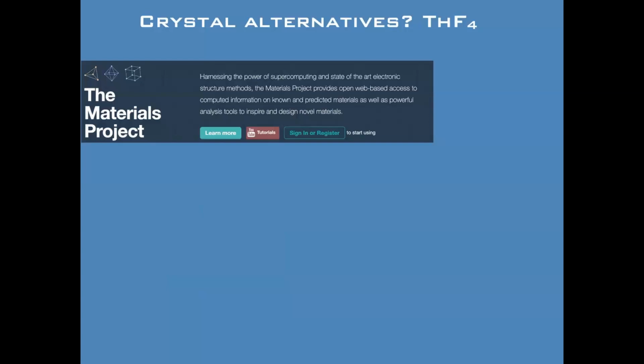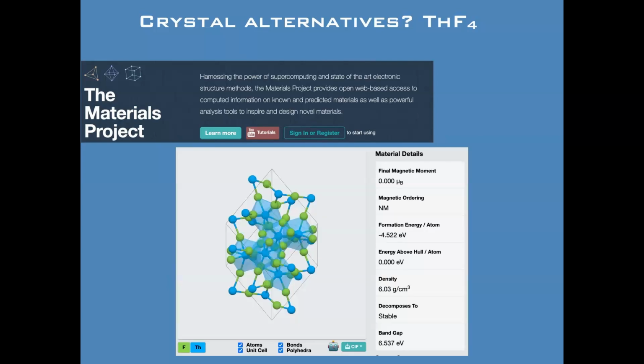But it would be nice if you didn't really have to dope into a crystal. If the thing you wanted to put in was native to that crystal anyway, then you don't get states within the band, and that's got to be helpful. So you immediately think of thorium fluoride. We had always wanted to use this, but if you go to the Materials Project, you pull it up, it'll tell you that the band gap is 6.5 eV. So that's well below the nuclear state. We can't use it. We can't get the light in, the nucleus will be quenched. It'll make a conduction electron, it'll never work.